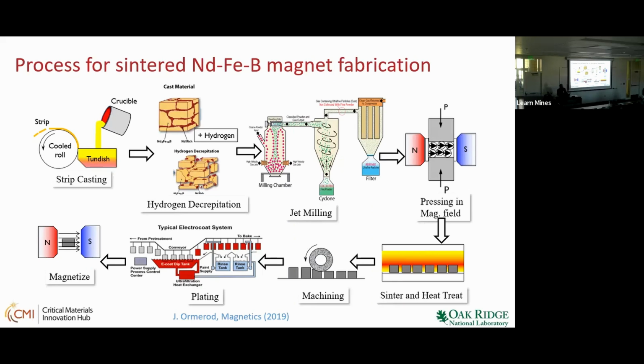Then once you make it, the way magnets are made is they are making large pieces, like huge. Then once you have the magnets made, you are doing the machining. That's where, in every step, from the strip casting, hydrogen decrepitation, jet milling, sieving and particle size variation, pressing the magnet, every step you will have some wastage. So that's where we are looking at how to recover some of these critical mineral materials from this wastage. Even with an efficient process, it could be only 70%, and 30% you may see is wastage.